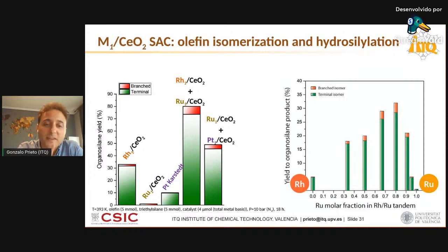We could go on. By the way, this is converting already an internal olefin. I'm not sure why the reaction is not showing on the top, but here we move from converting a terminal olefin to already converted octene. And that's why it was necessary to combine olefin double bond migration activity to bring the double bond to the end of the chain, plus this regioselective functionalization with the silane. If we move even to a farther internal olefin substrate, a more challenging substrate such as 3-octene, which is what I'm showing here on the right-hand side, then we can very clearly see the synergism between the two single atoms when combined in tandem.